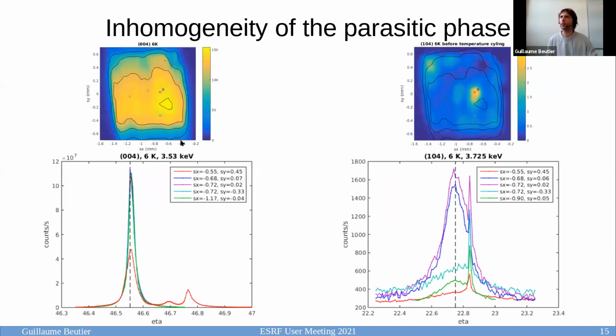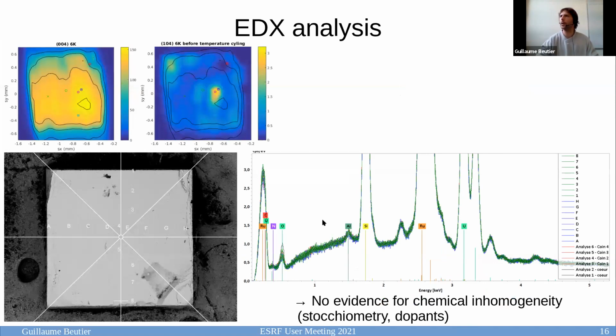So in more detail, you can look. We sampled the sample. I can show you some rocking curves, and you can see on the charge peak, it's very homogeneous everywhere you look at the sample, except here, because here there's clearly a notch in the crystal. But if you look at the same positions for the magnetic peak, you can see that the intensity and the width vary quite a lot. I'm discussing only this broad peak. This is some spurious peak here, which I don't know where it comes from.